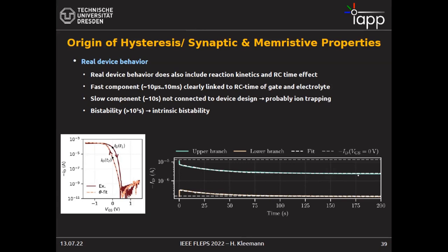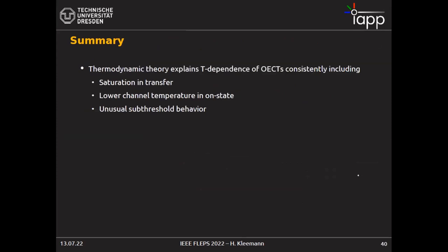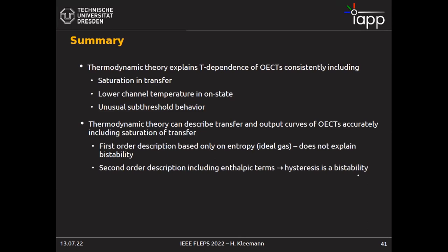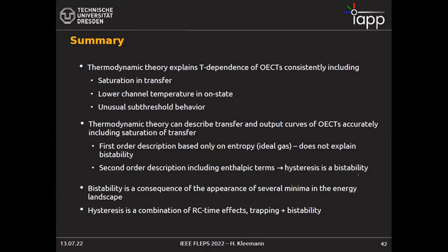The entire transient behavior of the device needs to be described by a combination of RC time effects, possibly more complex longer-term trapping, and this thermodynamic bistability. The model explains the saturation transfer curve, the channel cooling during operation due to the endothermic chemical reaction, the unusual sub-threshold behavior becoming steeper with increasing temperature, and — when we include enthalpic mixing — the bistability as a consequence of having two minima in the Gibbs free energy.